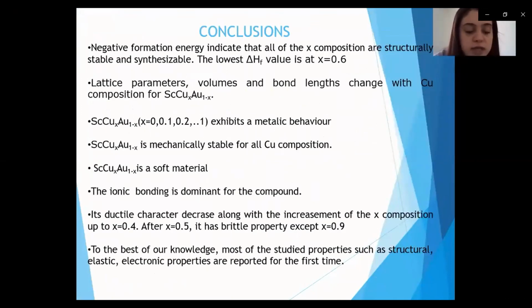The results we obtained at the end of this study are as follows. Negative formation energy indicates that all of the X compositions are structurally stable and synthesizable. The lowest delta H value is at X equals 0.6. Lattice parameters, volumes, and bond lengths change with copper composition for scandium copper gold. Scandium copper gold exhibits a metallic behavior. Scandium copper gold is mechanically stable for all copper compositions.